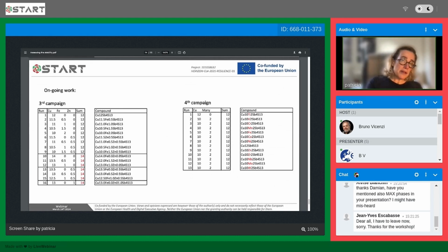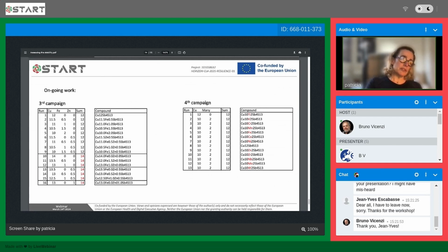So this is something we're trying to do in order to study the material from a fundamental point of view. And then another finding is that if you have excess of copper, usually the ZT is better. So in this case, what we're trying to do is to also study from the fundamental point of view and then validate with experimental results.